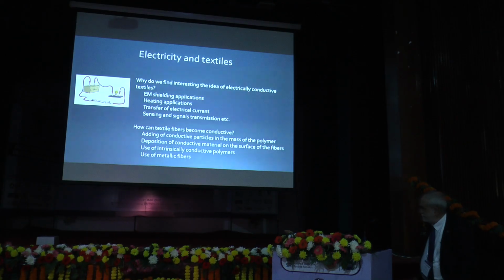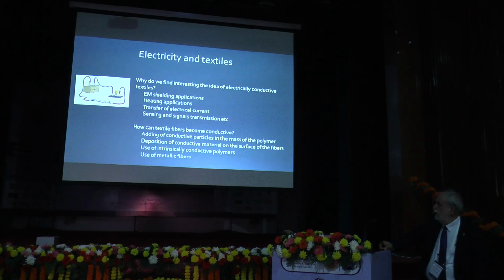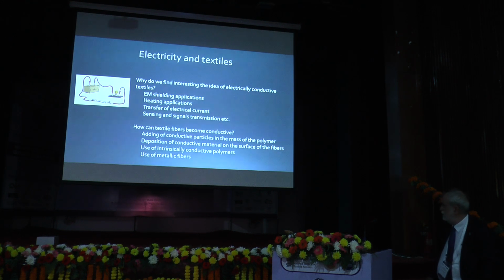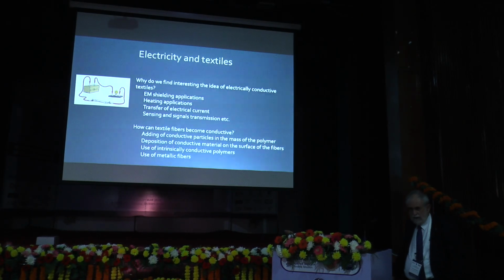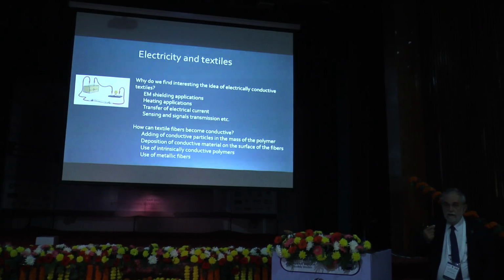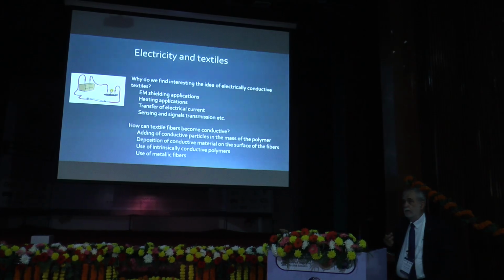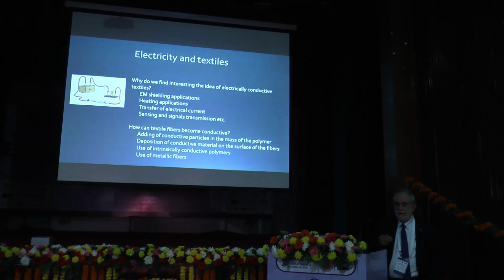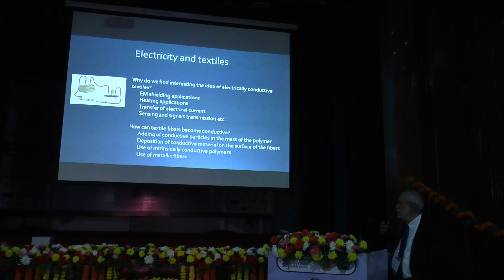The story with the conductive textile started in the decade of the '60s as a top secret research program in the United States and the Soviet Union, mainly for aerospace applications. And they had the first conductive fibers in this period. How can we get conductive fibers? By adding conductive particles, carbon or nanomaterials and so on in the polymer. Of course, if we want to have high conductivity, then we destroy the character of the polymeric uniformity. That means we reduce the textile properties. So we try to find a balance between conductivity and textile properties.